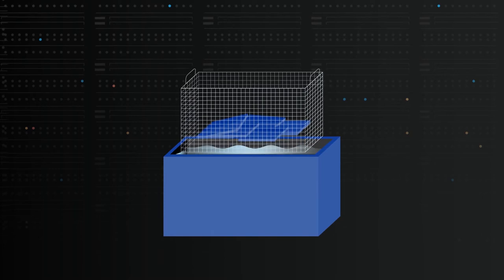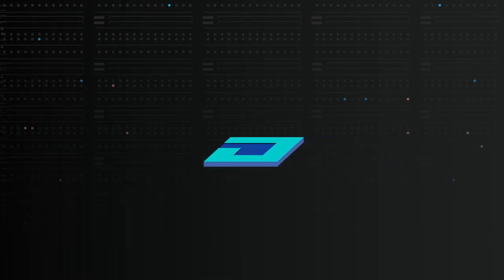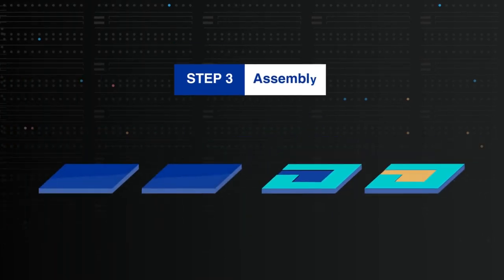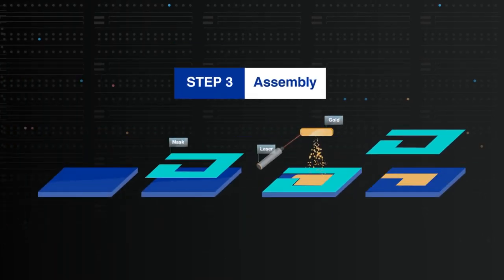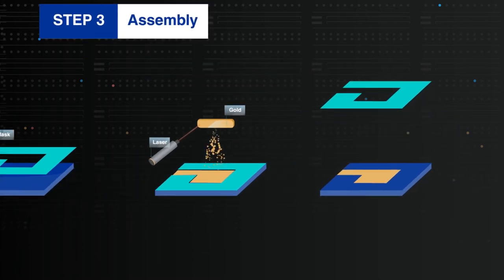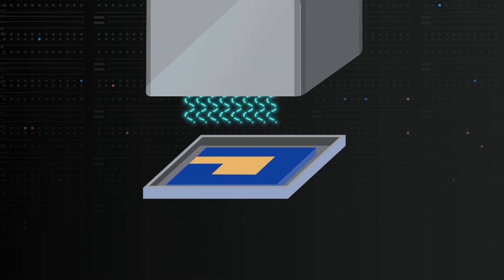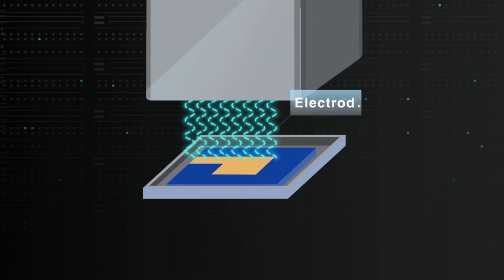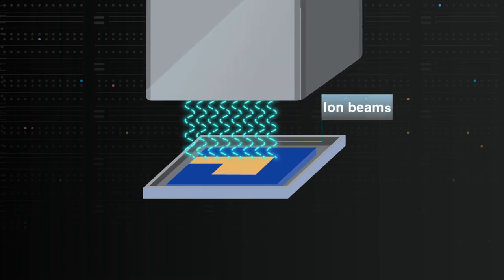During assembly, the crystal chips are cleaned before two metal electrodes are sputtered to it. The crystal is mounted inside the ceramic package with special conductive glue, and the metal electrode is trimmed until the crystal's desired oscillation frequency is reached.